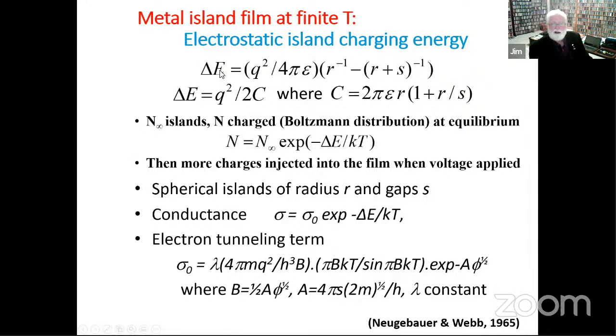And this is an expression of the electrostatic charging energy. It's the energy to remove an electron from an island of radius r to the next island a distance s away. And so the number of charged islands would be given by a Boltzmann distribution at equilibrium. This was the classical model, but it's pretty well established now that more charges are injected into the film when voltage is applied, and that number swamps this number. And the tunneling is given by a normal tunneling term of this form.